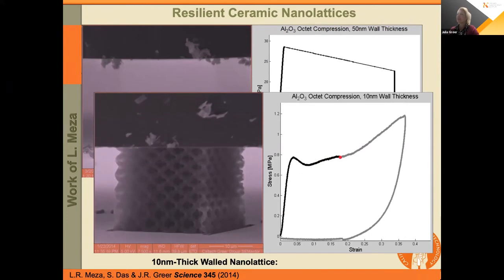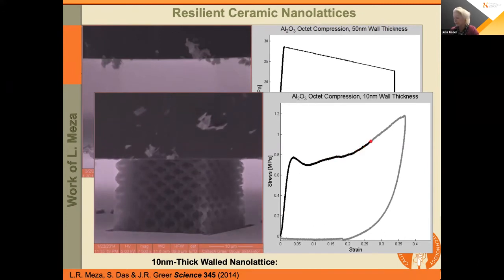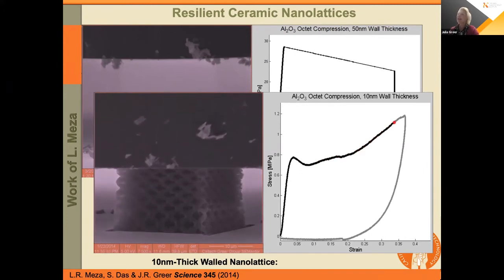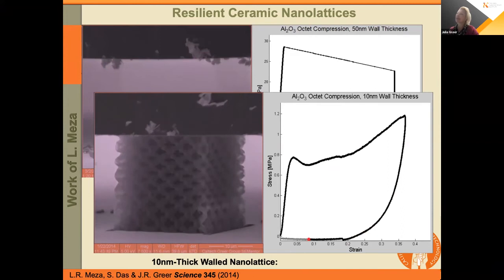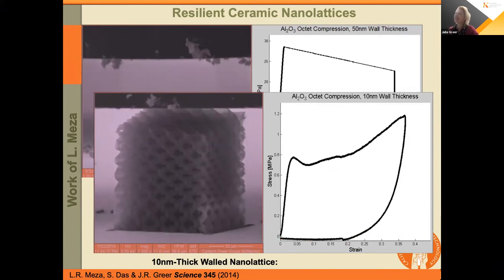So we are compressing it, and we're expecting it to crush and die and to shatter. And we're compressing it by more than 50% in many cases. And this particular ceramic thinks that it's a sponge. So if this doesn't convince you that there's a size effect, and that there's a nano-induced size effect that can be proliferated onto larger dimensions, then I should just stop talking about this phenomenon altogether.